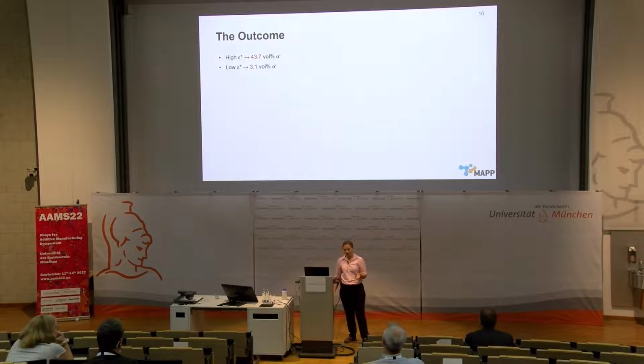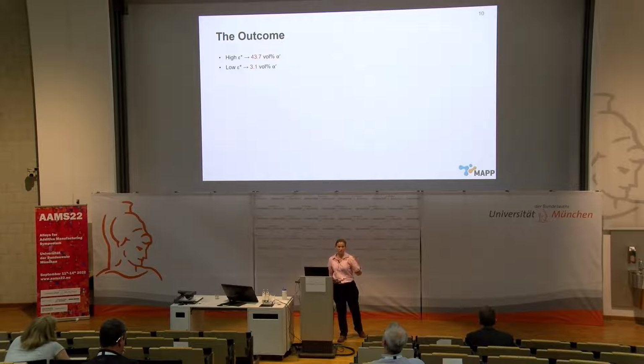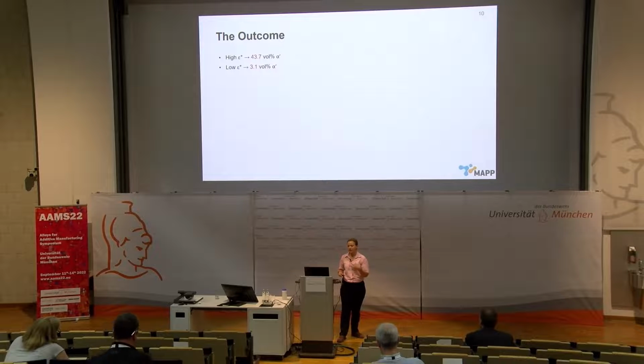But in terms of the outcome, so our high strain parameter, we've got around 43–44% of martensite. So that's our strong brittle phase, and therefore we've got around 55% austenite, which is our weak ductile phase. With our low strain parameters, we only get 3% martensite. So already we've seen perfect, good, we've achieved what we wanted in terms of our phases. Does it make a difference to what's happening?